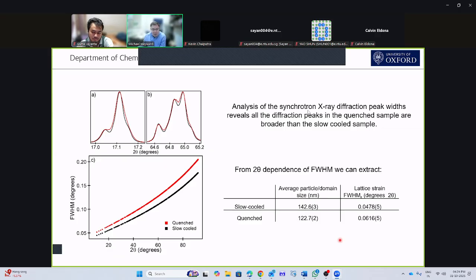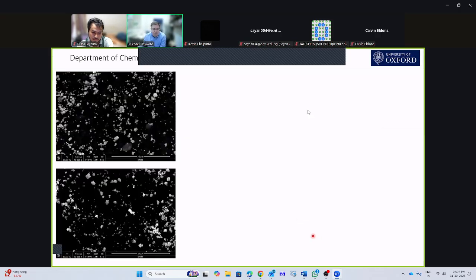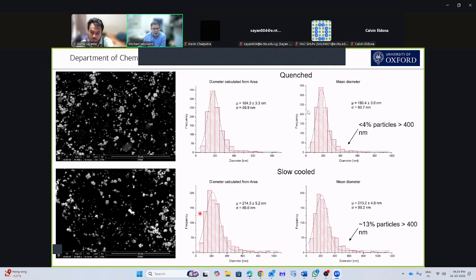Now we can check, or at least we can check the particle size, by doing an SEM measurement. So what we're doing is basically taking a picture of the particles, and then we can fit their sizes and show, yes, indeed, the quenched samples do have smaller particle sizes than the slow cooled. And the critical point is that the quenched sample doesn't really have any big particles, whereas the slow cooled sample has a number of particles greater than 400 nanometers.